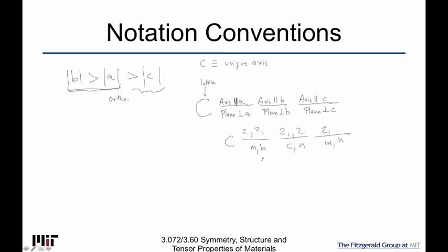For orthorhombic, the convention is that the symmetries that aren't screws, in other words, the higher symmetry axes, dominate over the screw axes, which are less symmetric. And then in terms of the glide and mirror planes, the mirror plane dominates, and then the glides follow a convention, and D is last.